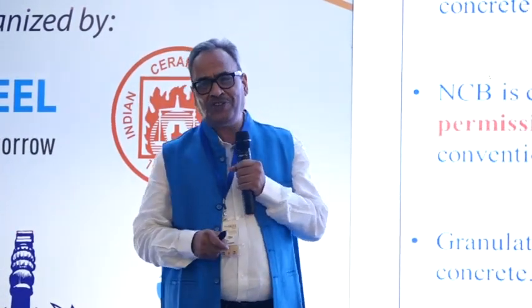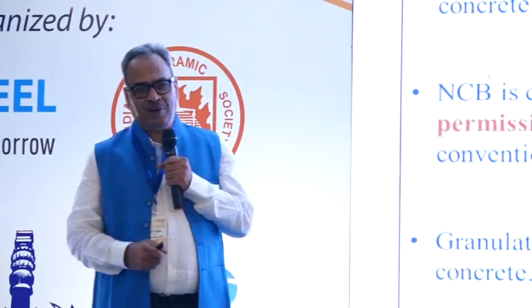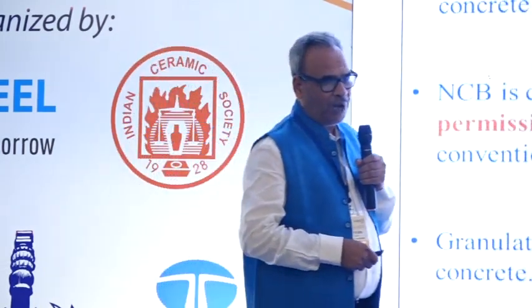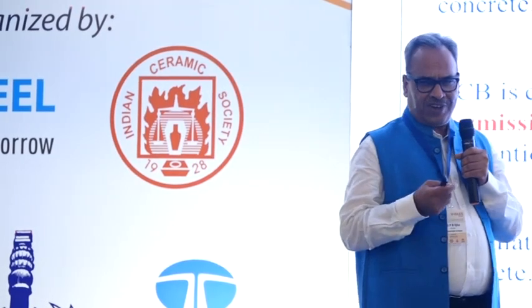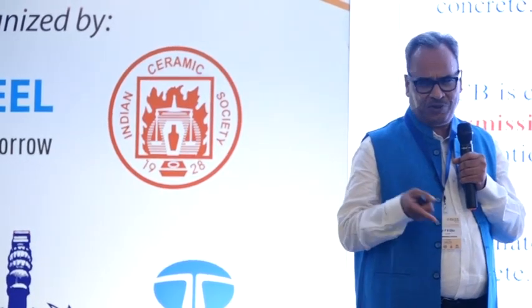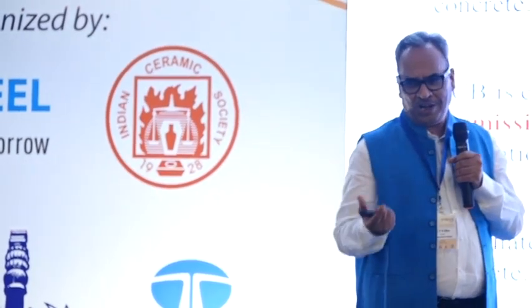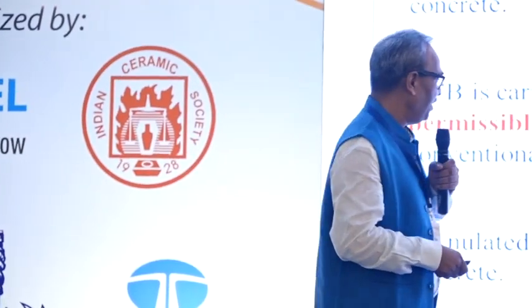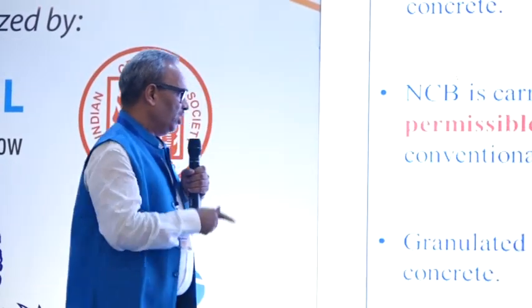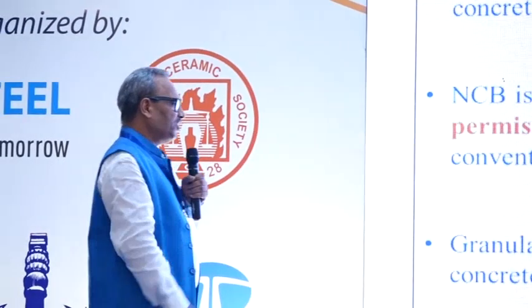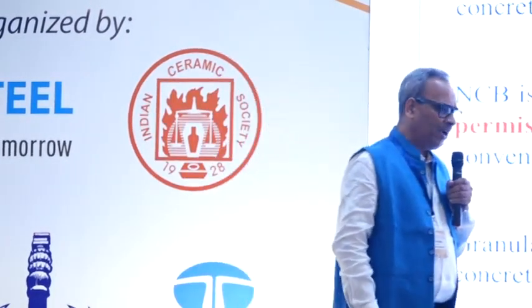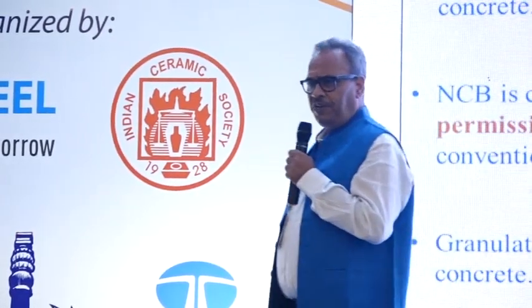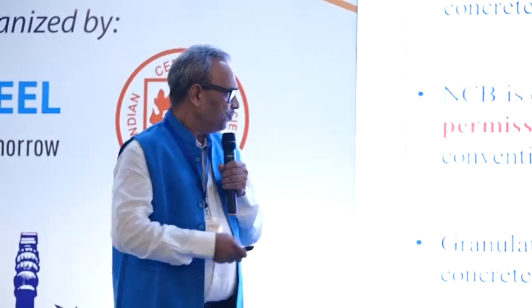So the hypothesis is being tested at our laboratory. We start from the null hypothesis, and if it is proved wrong, the alternate hypothesis will be accepted, right? So it is being done by replacing at 0, 25, 50, 75 and 100%, and based on that, it can be recommended that it can be used up to 100%.